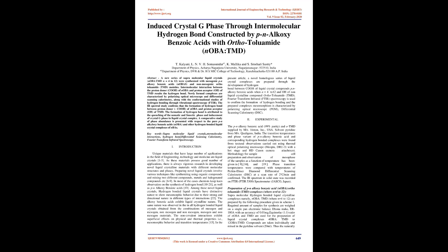Intermolecular interaction between the proton donor, COOH, of nOBA and proton acceptor, O, of TMD results in the hydrogen bond. Newly formed complexes are characterized by polarizing optical microscope and differential scanning calorimetry, along with the conformational studies of hydrogen bonding through vibrational spectroscopy, FTIR.